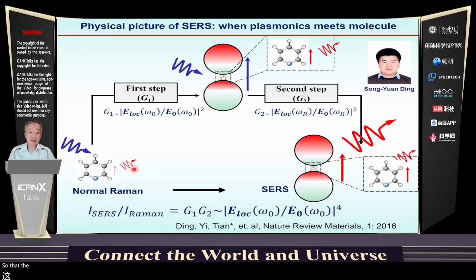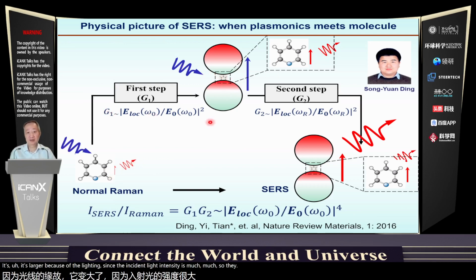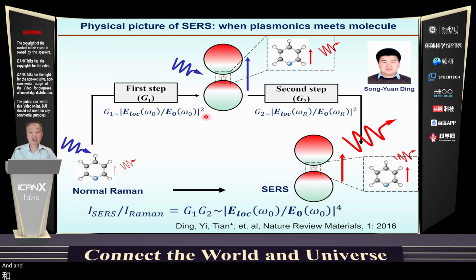So the Raman scattering signal in comparison with this is larger because the incident light intensity is much larger. This is the first step, because the intensity is proportional to the field strength in a square relationship. Then the second step is about the emission, because a nanoparticle is so smart.